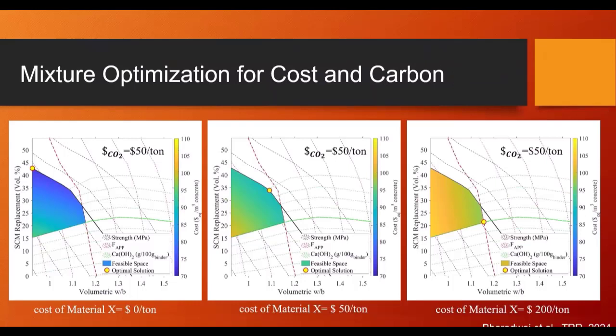The final thing that we're doing here is we're actually mathematically optimizing these systems. So a very simple add-on at the end of this program, all right, that we're doing is we're saying, let's take that feasible region that we had before, SCM replacement versus water to cement ratio. The one little trick I did between slide 25 and now is I switched this over to volumetric water to cement ratio because here's a little secret. Not all SCMs have the same specific gravity as cement, right?